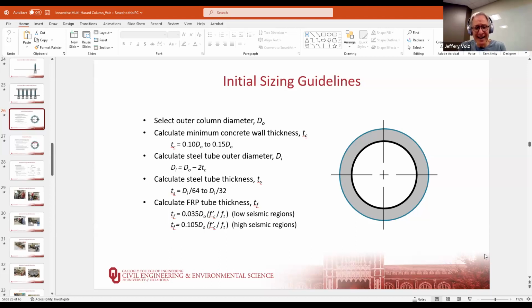Excuse me. And again, those ratios for the steel tube, the 1/64th at the lower end, that'll give you the thinnest. Then you're going to have a tendency for a little more potential for buckling. As you make it thicker, you'll have less buckling at the 1/32nd. And then if you're in a high seismic region, you're going to want that thicker FRP thickness because you're going to have much higher strains. That's the big thing about seismic. It isn't necessarily that the forces are higher than you would get from perhaps some other type of vehicular loading or something else. The strains are so high because the displacements are so high.